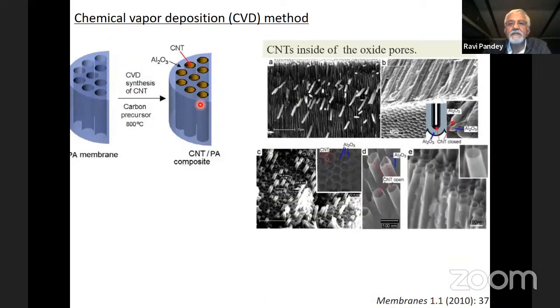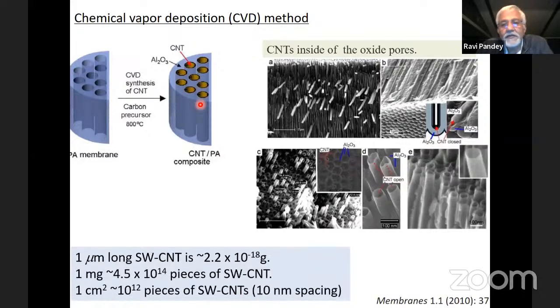So this again is just to give you an idea about the CVD method, which is commonly used to grow these nanotubes. We have the organic membrane, and what you do is use the precursor at 800 degrees Celsius, simply deposit, and what you have is nice bundles of these carbon nanotubes within these oxide pores. This is quite a common approach.